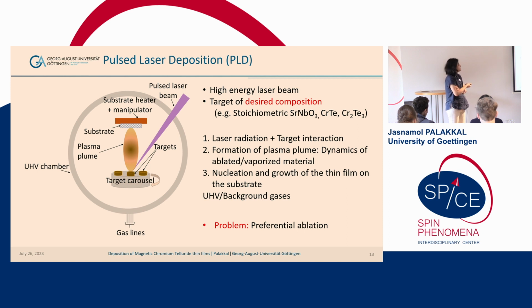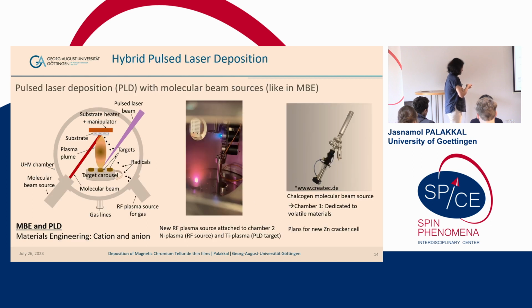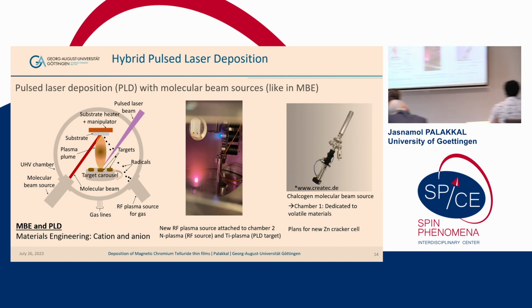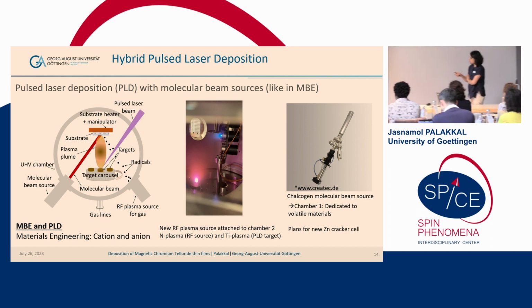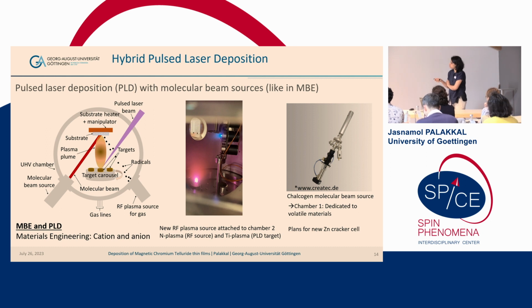And in such cases, you have to use MBE, but as I said, MBE also has many disadvantages when you grow materials containing many cations. And that's the main reason why we are developing the hybrid pulsed laser deposition technique. In this case, you can directly deposit the material.